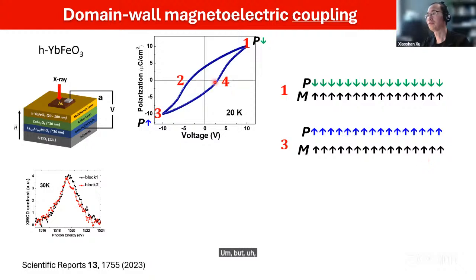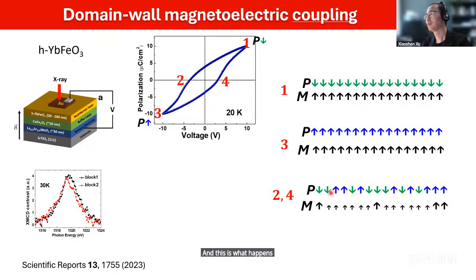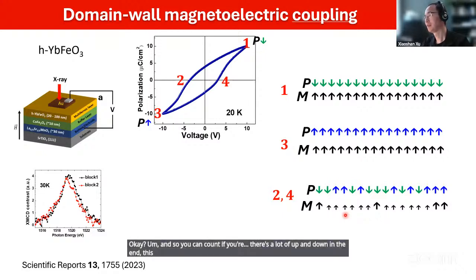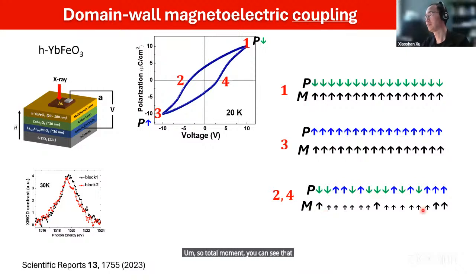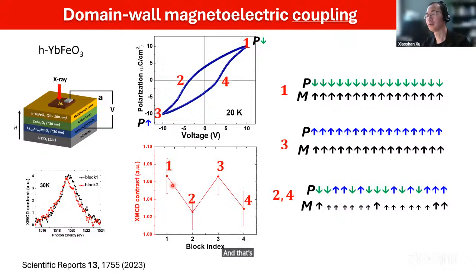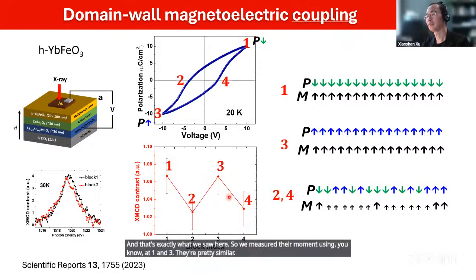But for points 2 and 4, this is what happens. All the moments have to add up to be 0, so that means there's a lot of up and down. Every time you switch between up and down, as we talked about a moment ago, the magnetic system is unhappy, or too busy to follow this change. So they have a little less moment here. You can count that if there's a lot of up and down, in the end this is what you get. So the total moment is quite different in this case, and that's exactly what we saw here. We measured their moment, and at 1 and 3, they're pretty similar. At 2 and 4, they're not exactly the same.